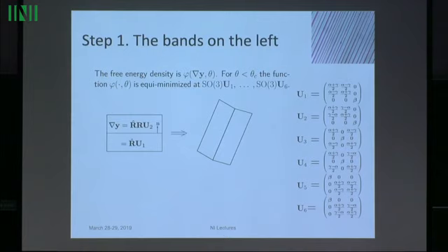for this U1 and this U2, or in fact it could be other pairs, any pair actually, then there exists an R such that these differ by a rank 1 matrix. The R hat doesn't matter because it pre-multiplies the whole equation. So there exists exactly 2 R's. So in some sense, up to overall rotation, there are 2 solutions to this equation. I've pictured one of them here.